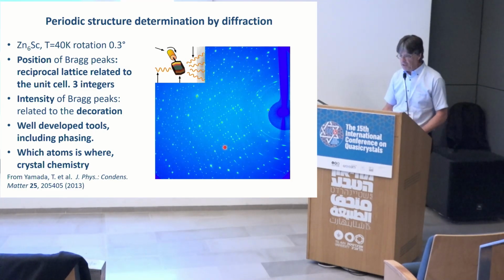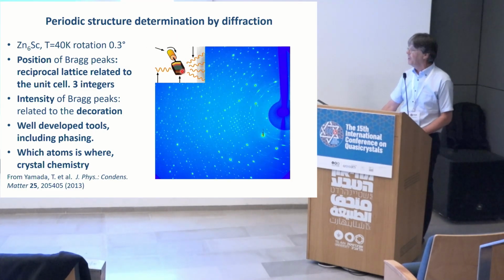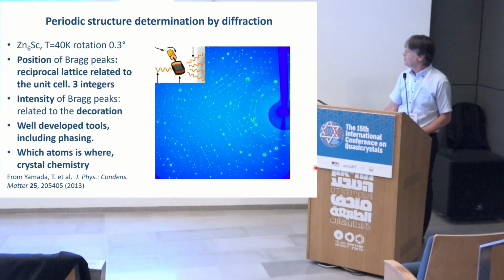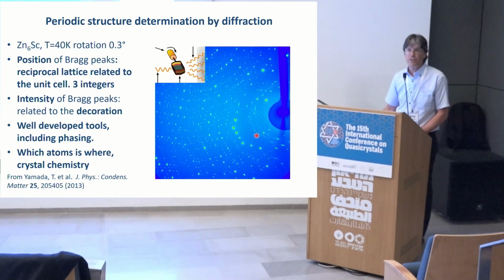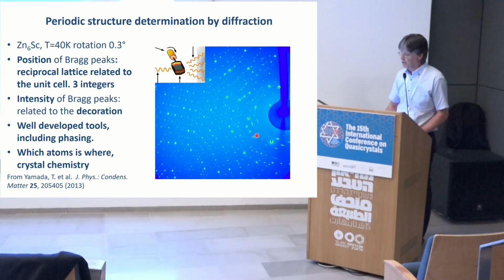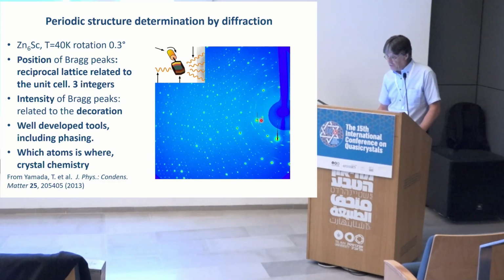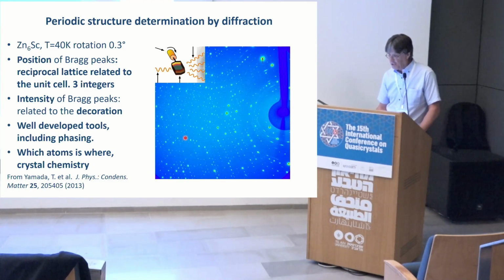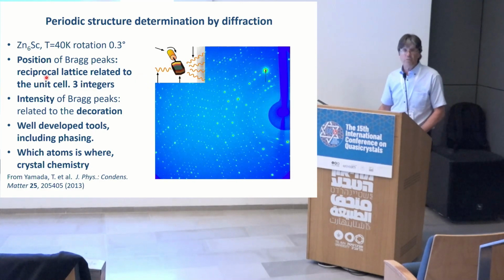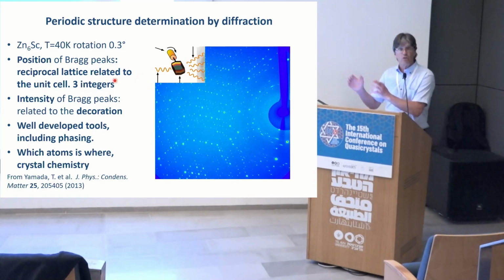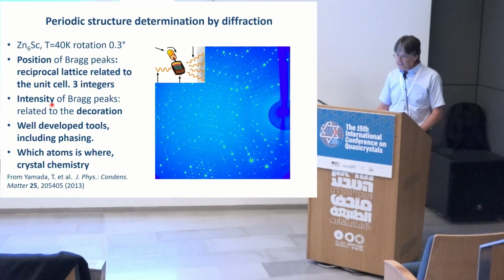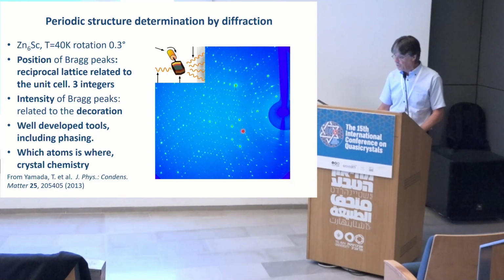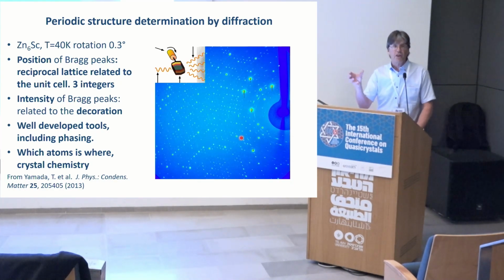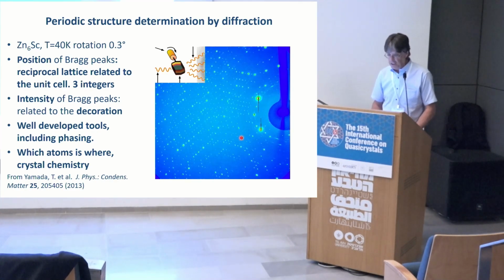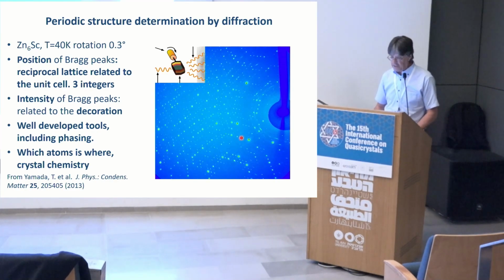And doing an experiment is pretty simple. You have your crystal here, you rotate it, and this is what you see exactly on your detector, taken on a zinc scandium system. You see that you have a strong Bragg peak, weaker ones, but they can all be indexed with three integers because this is a periodic structure. And the intensity of the Bragg peaks that you're seeing here is related to the decoration. So the encoding of the decoration is within the intensity.